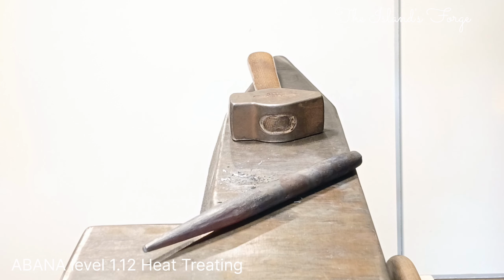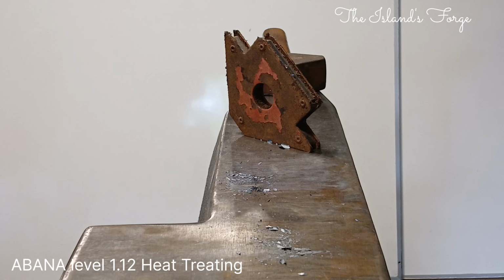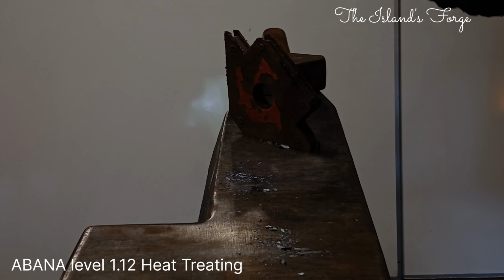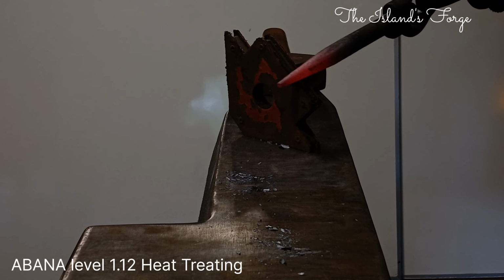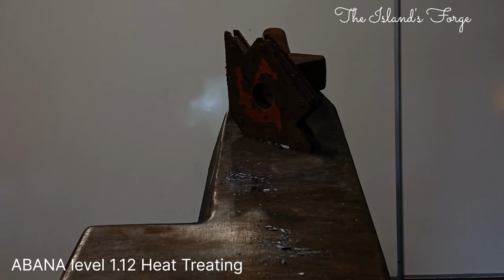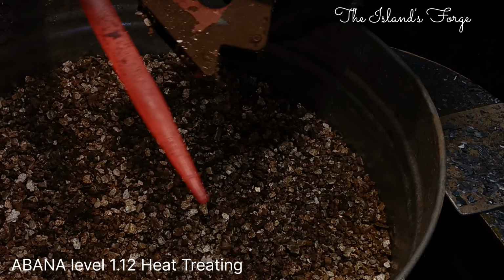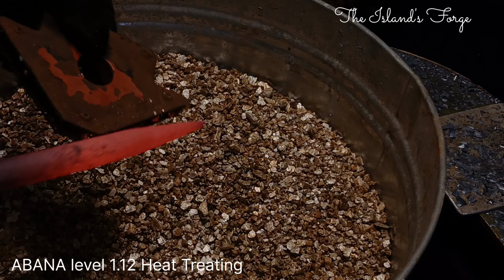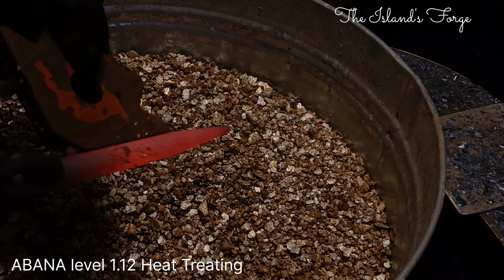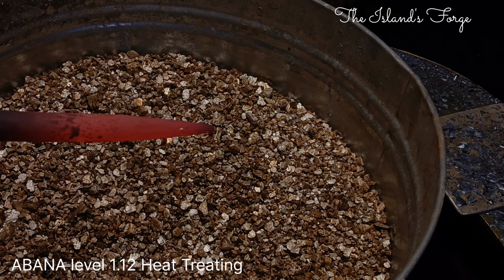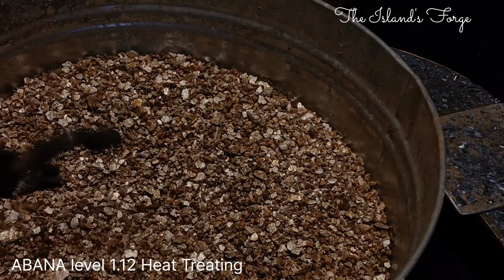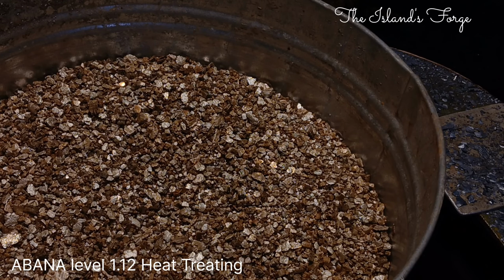So here's our round punch, and we're going to begin by normalizing it. We heat the tip until we get it non-magnetic. So there it is. You can see the way the main part is magnetic, the tip isn't. So we just leave that on the side of the fire to air cool. So here we are showing how to anneal it then. After the normalizing is done and it's cooled, we anneal it, get the whole bar non-magnetic and push it then into the vermiculite. Leave overnight.